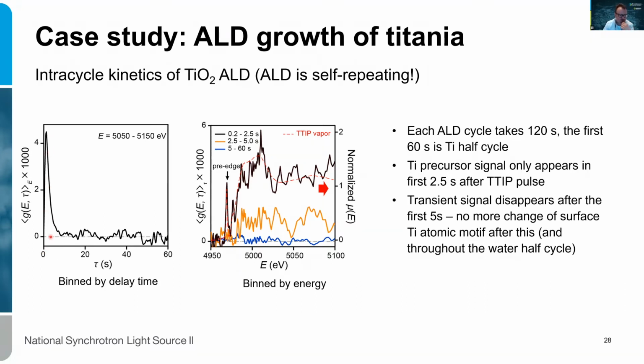And you see this strong peak right here, which is essentially the precursor vapor that goes in and is pumped out, and whatever is left on the surface remains, which is this yellow component, which is not very pronounced, but that corresponds to just this region, 2 to 5 seconds after the pulse, when the gaseous precursor is gone. So we essentially can get a better time resolution from this process than the length of the scan.